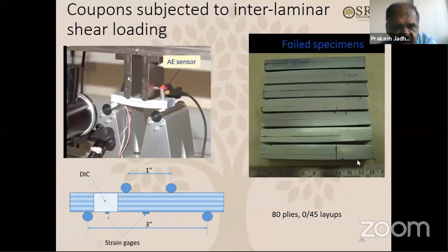So, yeah, this is what we were doing here. As you can see, this is the short beam shear specimen. Short beam shear generally is done in 3-point bend, but we were doing 4-point bend here, because we found it more convenient, and because we have enough space for putting the strain gauges and the acoustic emission sensor. So this is the acoustic emission sensor basically. It measures the number of sound events.